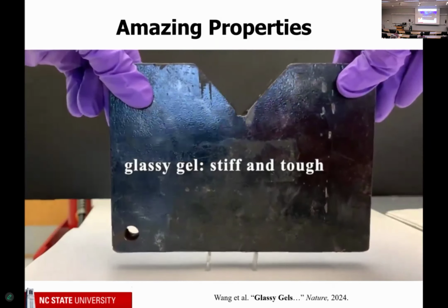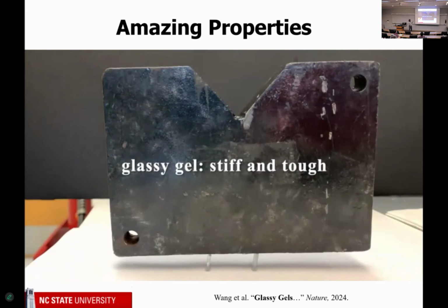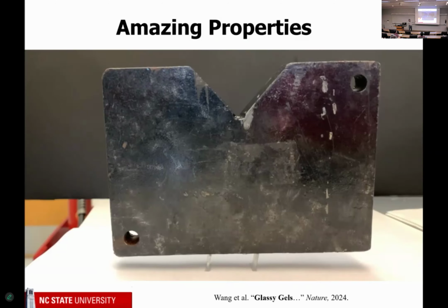And this is like a dried out contact lens. But here we form what we call a glassy gel, which is a material that contains 60% liquid, just like the hydrogel, but it's using ionic liquid. And the ionic liquid makes the material very strong despite containing a lot of liquid. And so it's the same polymer as the other two. It's just this one's very, very hard despite having the liquid. And the advantage of having the liquid is that it can make it conductive, and then it also makes it very stretchable.